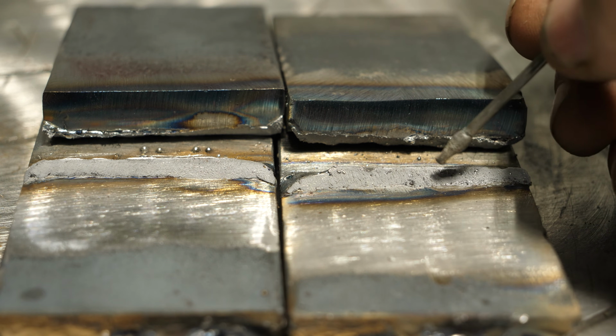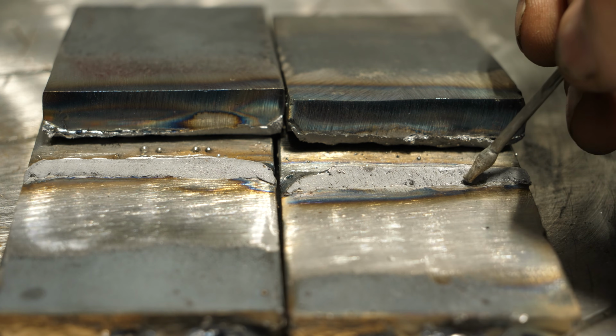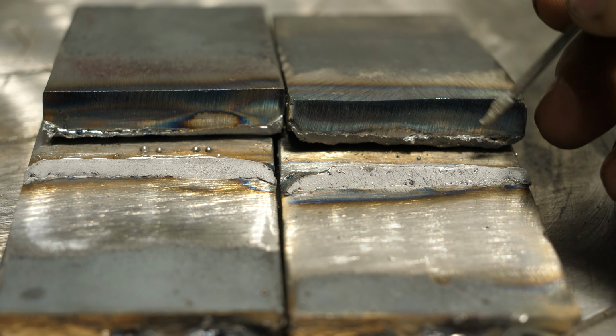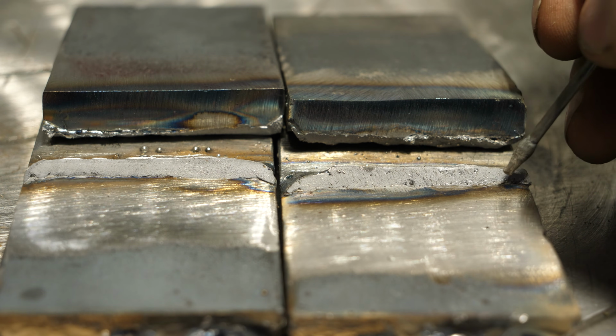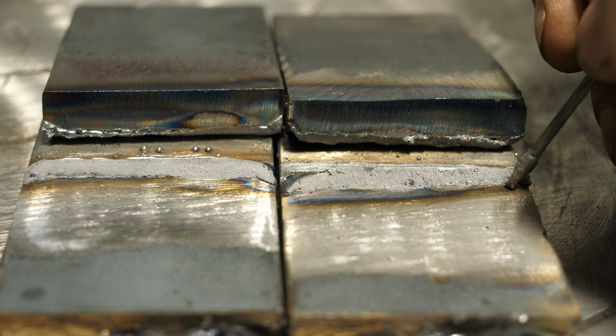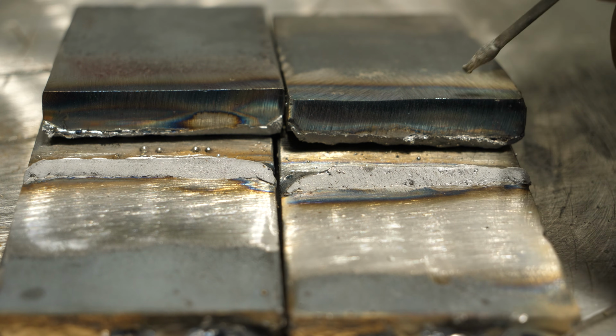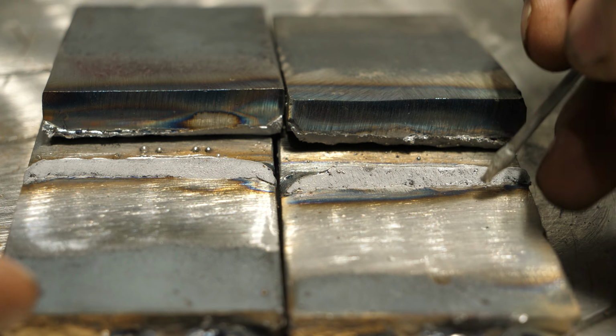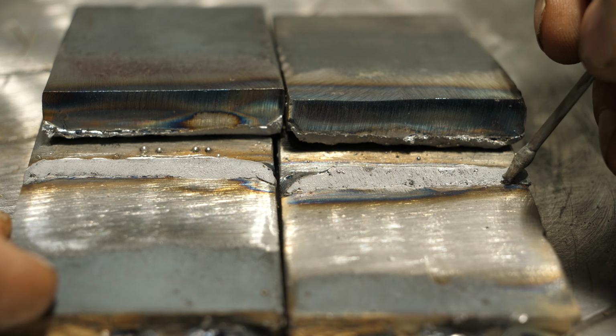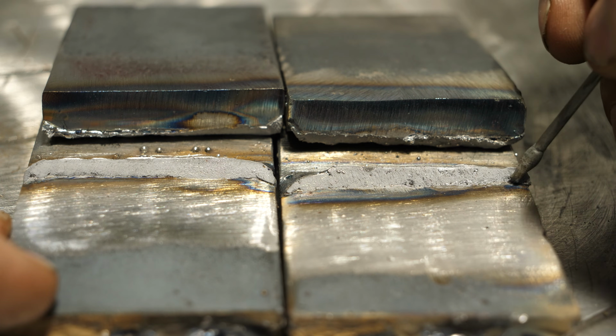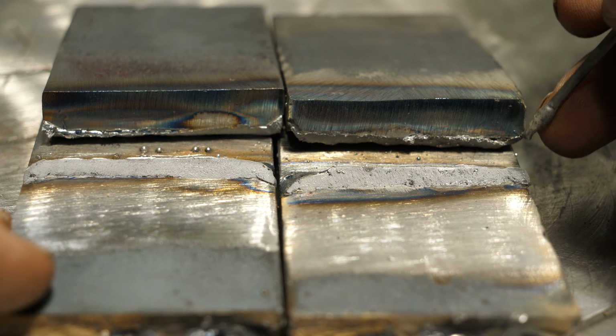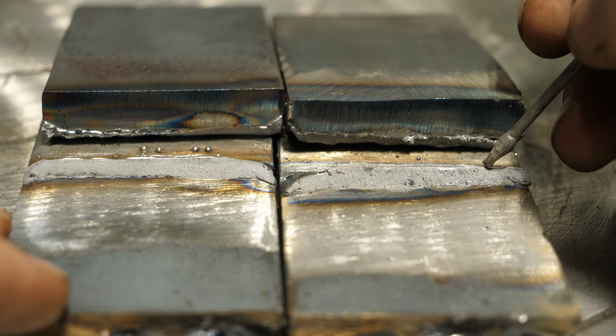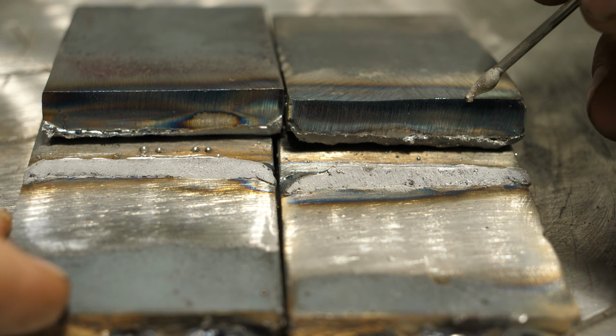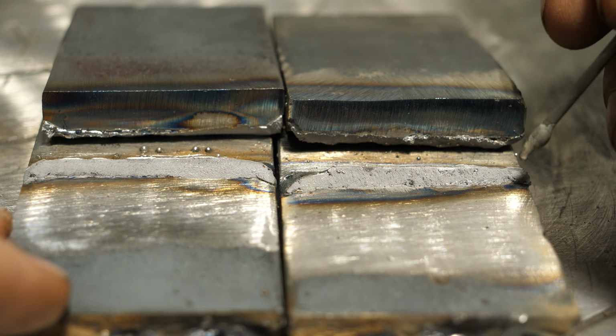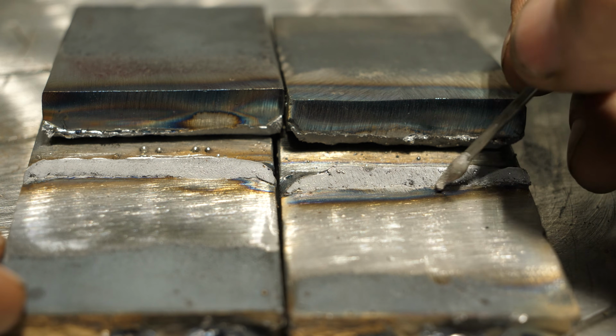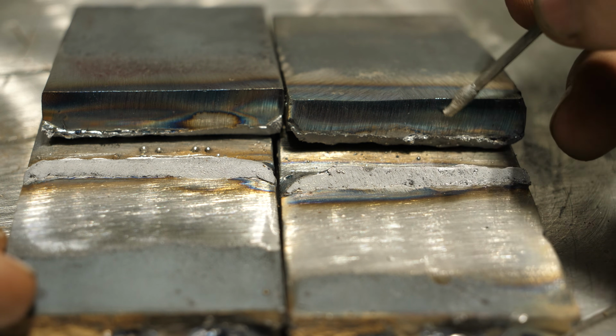And like I had said earlier in the video, this flux core wire and all of them that I have either don't say max thickness or they say some oddball size that's under 3/8. So none of them that I had is rated technically for 3/8 plate. So I think we're seeing defects that just go along with welding on this thick a plate, which, had I been running more amperage with a bigger wire, could have safely welded this. But that's a very good bit of information if you're ever faced with welding very thick metal like this with flux core wire. Everything that I did, I mean, I'm telling you guys, I did a ton of testing.